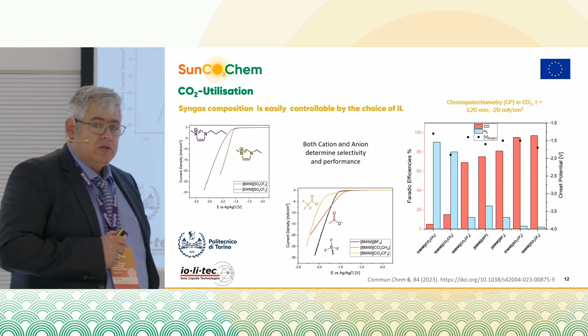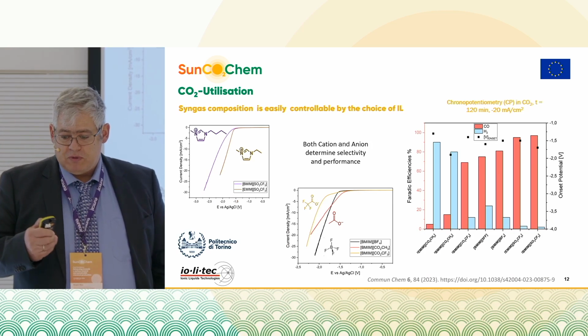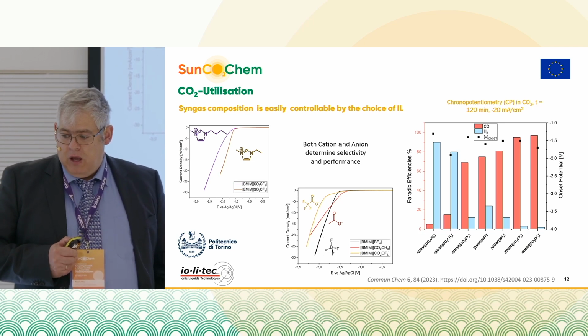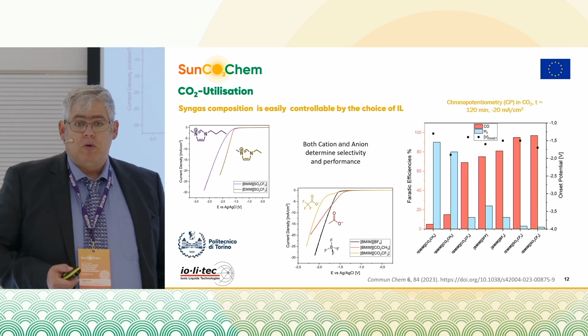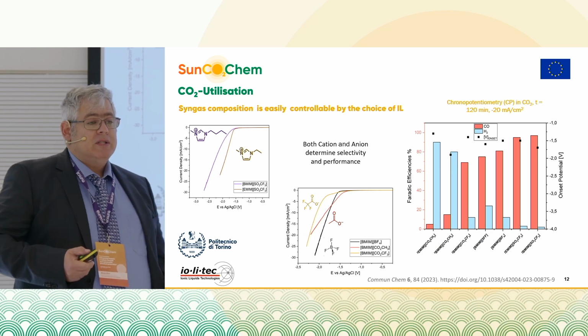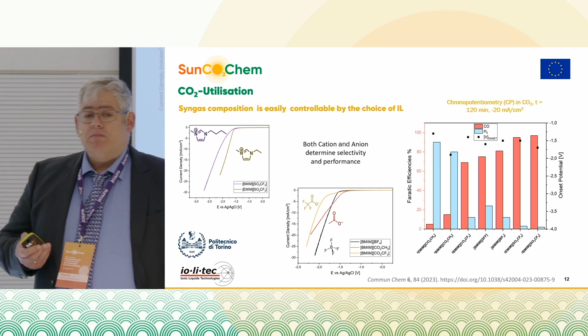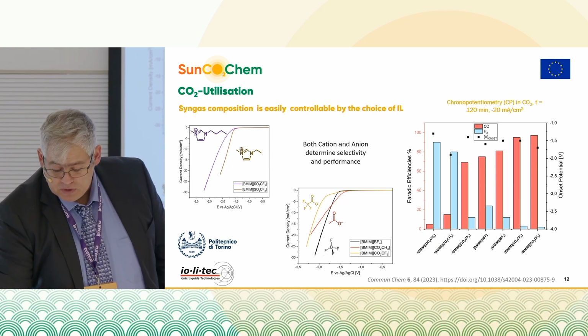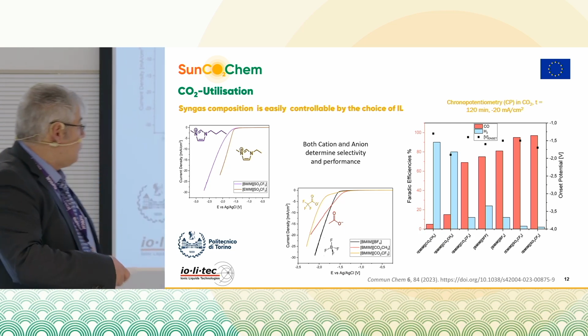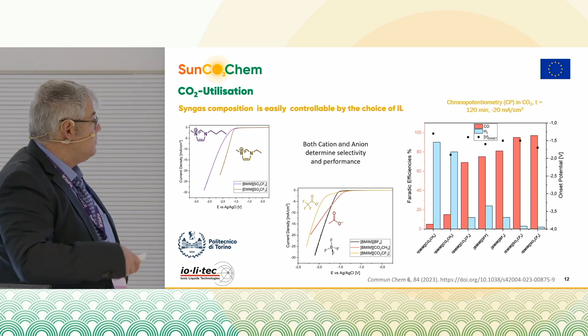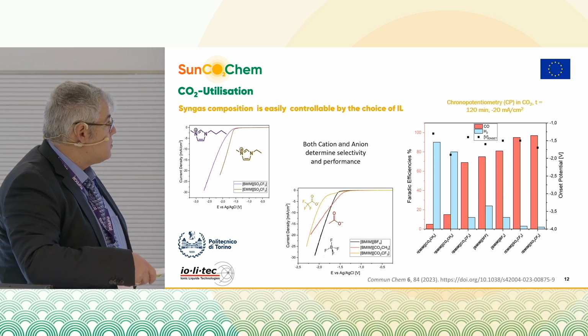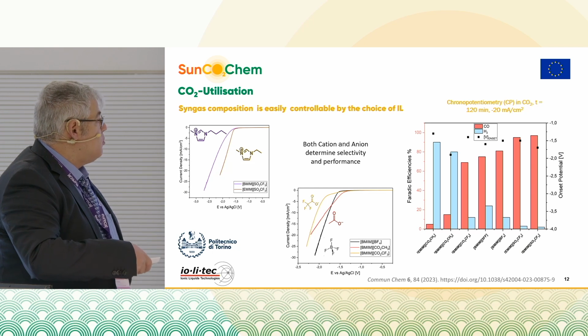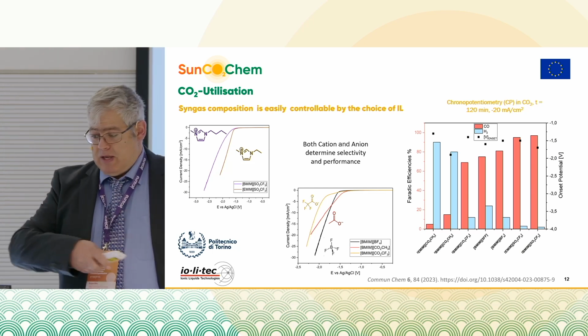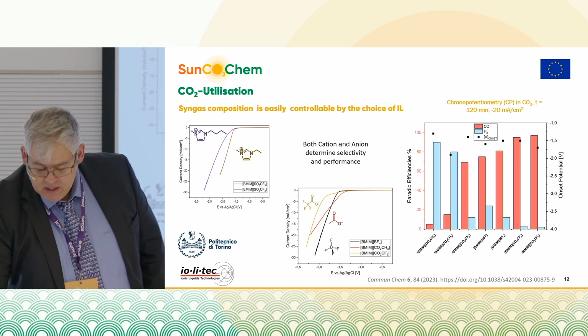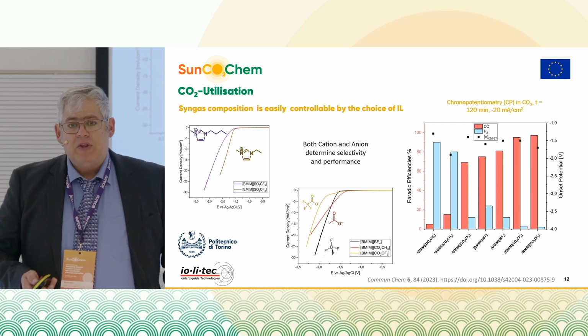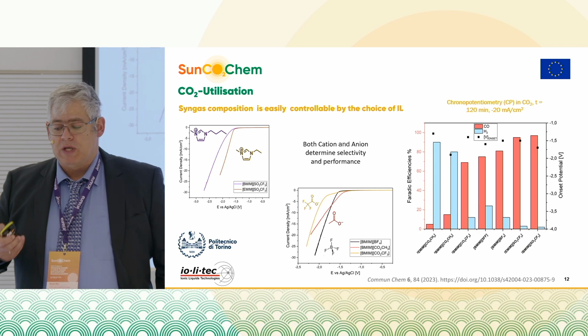The really nice thing I mentioned just a few minutes ago about the results from the Polytechnico is that depending on the ionic liquid or the ionic liquid composition in your mixture, you can very nicely and very finely tune the composition of your syngas or what you're producing. As you can see here from the left, from almost pure CO to the right, well, the other way around, of course, almost pure hydrogen to almost pure CO. And anything in between. So this is a very easy, very versatile method of fine-tuning your gas composition.